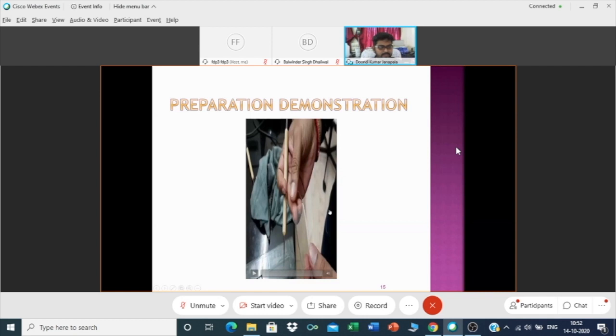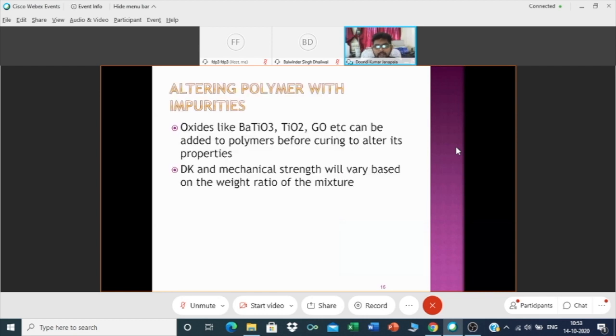So this is the demonstration of the preparation of the simple polymer PDMS, polydimethylsiloxane. Now, what you can do next: this polymer at 2.4 GHz will have a dielectric constant of 2.6 to 2.7 with a loss tangent of 0.0314. That particular low dielectric property is one thing that makes it a very suitable candidate for working with wearable antennas, and you will get a good bandwidth while working with this PDMS.